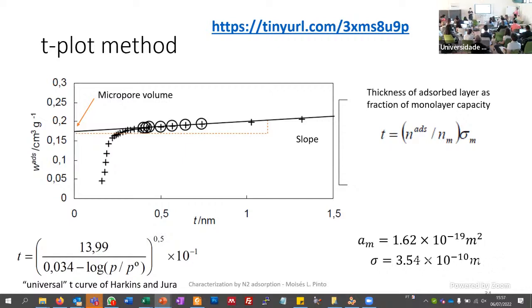So actually, from a more pragmatic point of view, you take your column where you have P over P0, you transform this column into thickness. Then you have your x and your volume in here. Then you do the plot. You should obtain something like this. And if you remember, 0.354 is more or less the thickness of the monolayer, so 0.354 in terms of nanometers, 3.54 in terms of angstrom here. So what you should try to do is, in this range, fit a line, and then extrapolate to see where is the intersection.